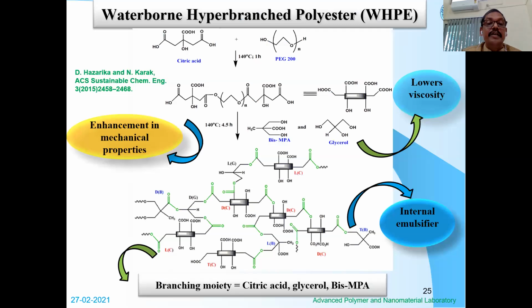In this, we have synthesized a water-borne hyperbranched polyester using citric acid and glycerol as the bio-based raw material along with others. In this strategy, we have not used any solvent, any catalyst, any neutralizing agent to get the water-borne system. Thus it is really an environmentally benign system, and the polymer exhibited very unique attributes.